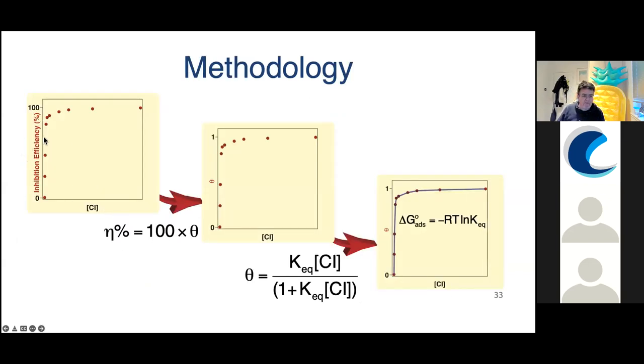So here is our experimental data from a particular example system. This is inhibition efficiency versus inhibitor concentration, and you can see it has this typical asymptotic plot for an organic corrosion inhibitor. They then assume the efficiency is related to the coverage theta, the fractional surface coverage, where the maximum coverage equals one, going from zero to one. Multiplying theta by 100 gives you efficiency. So according to this work, you can easily get theta from the inhibition efficiency, and that's plotted.